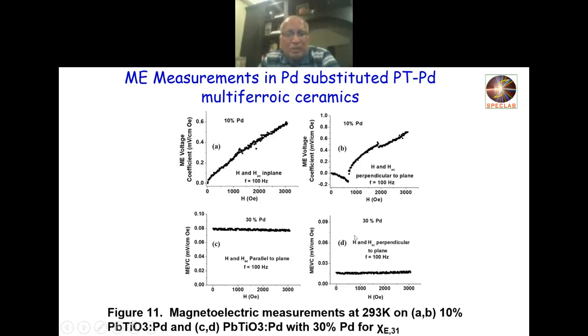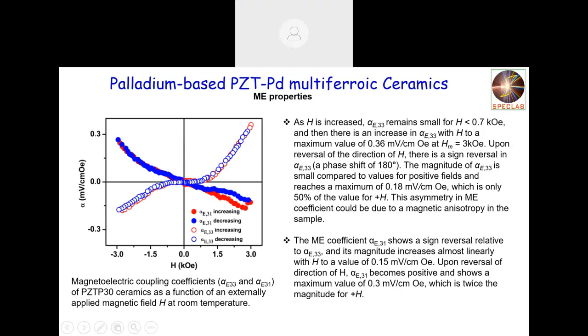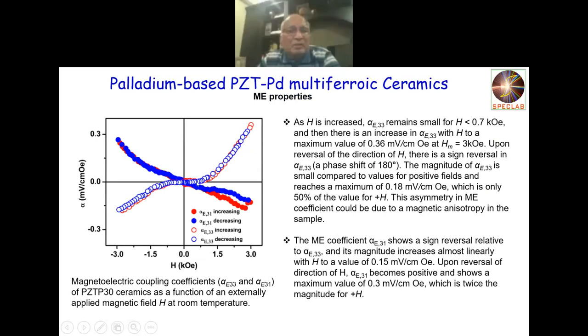But it did show a magnetoelectric coefficient, and this is a kind of material in which the doping is taking place at a site which is very different compared to the normal multiferroic, the other ones that we have talked about. And so there's a lot of future for these materials to be studied. Here are magnetoelectric coupling coefficients which we measured with Dr. Srinivasan. And again, we got magnetoelectric coupling of up to 0.3 millivolts per centimeter Oersted.